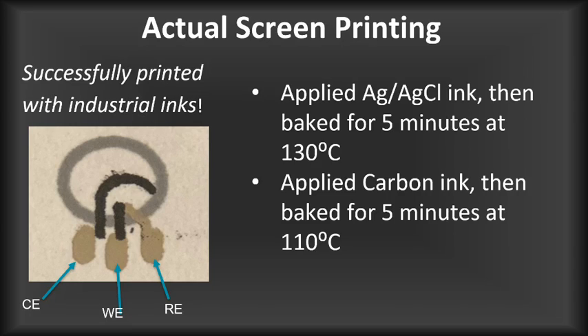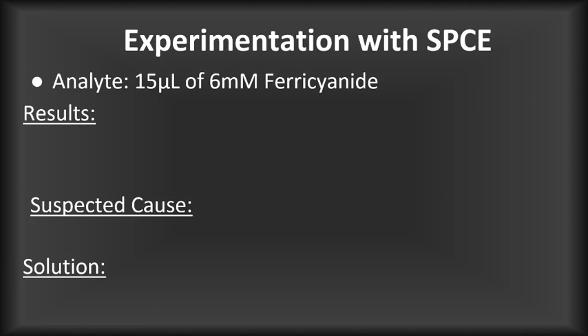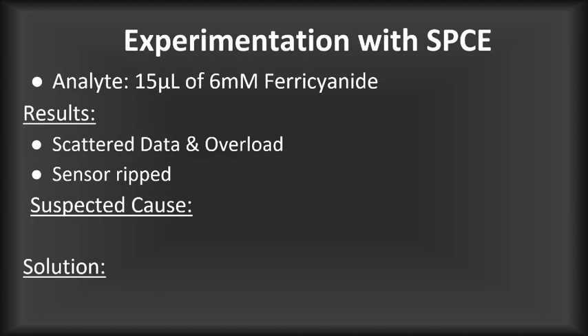And so, once we had successfully printed a carbon electrode, we needed to test it out. So, Darlene, my lab partner, did that with 15 microliters of 6 millimolar ferricyanide, a common chemical used in this type of analyses because it has a well-defined and well-known oxidation peak. The results: scattered data and overload. And to make matters worse, our sensor ripped.